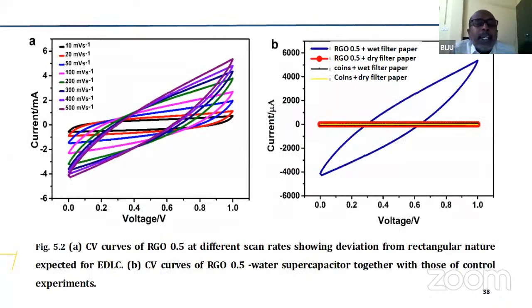See, one can see on the left-hand side the cyclic voltammograms of the RGO pure water supercapacitor at different scan rates, starting from 10 millivolt per second to 500 millivolt per second. In fact, the area enclosed by the curve can be considered as a measure of the energy stored by the device. Now, on the right-hand side, we are showing the performance of different combinations. The yellow one shows the coins, which means the electrodes, the metal current collectors, along with a dry filter paper. You can see that practically no energy is stored, as the area enclosed is practically zero. And when the coins and a wet filter paper are there, the black curve on the right-hand side also encloses practically no area.